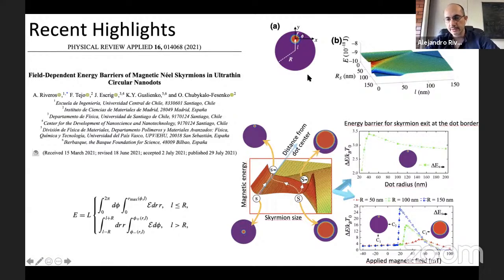We will be able to obtain the energy barrier for the annihilation of the skyrmion by three mechanisms: contraction, expansion, and deviation. The lowest energy barrier is shown here at zero field and under the field. The lowest energy barrier is very small at zero field, showing that the skyrmion will be quickly annihilated by thermal fluctuation. Nevertheless, it is interesting to show that the lifetime stability of the skyrmion is enhanced by applying a magnetic field perpendicular to the sample, reaching values close to 30 kT0, enabling the skyrmion to live for several hours before it is annihilated at the border.